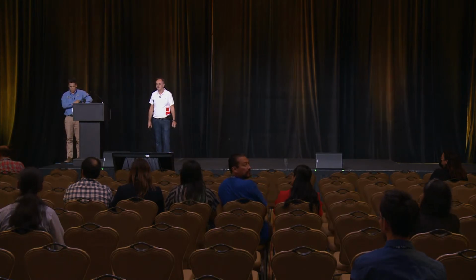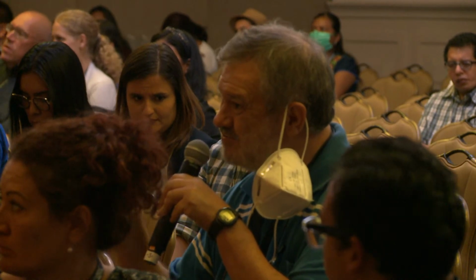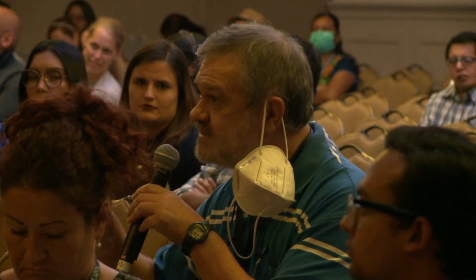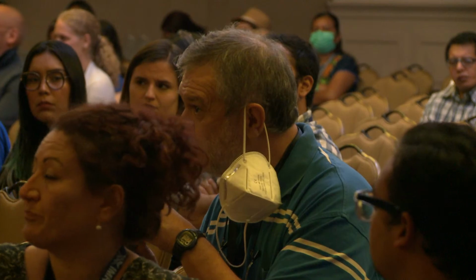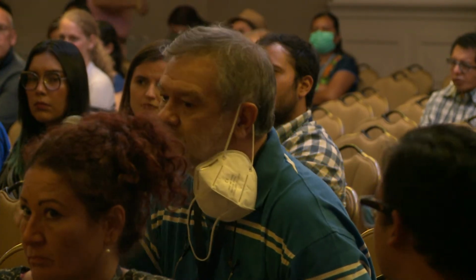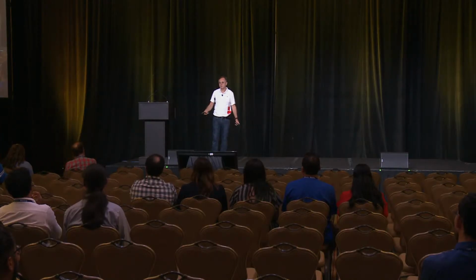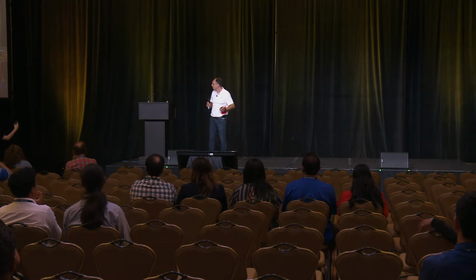Thank you. At the last part of your talk, you showed that you do not need gold, and that the highly damped plasmon of iron is enough. I'm surprised because the plasmon of iron is quite in a different energy range. Usually we use gold. The secret is that you are depositing the iron in vacuum, so it is metallic iron. It's not the oxide. That is the difference with the conventional oxide nanoparticles. If we had iron oxide, we would not have a plasmonic resonance, even a damped one. It's gone, my presentation. I cannot show you.